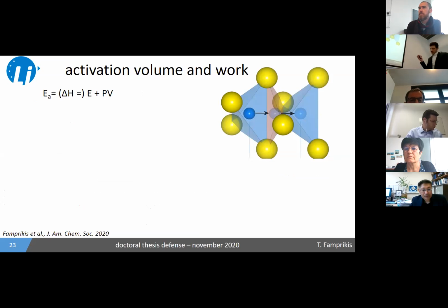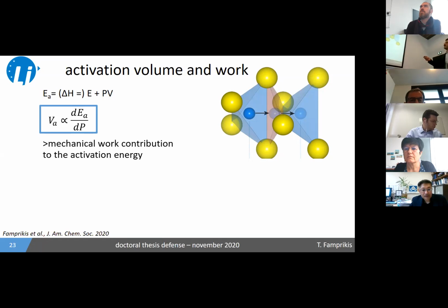remember that what we call an activation energy is more rigorously defined as an activation enthalpy. And as an enthalpy, it has an energy component and a mechanical work component. So the activation volume is nothing else but this volume component here, and it describes basically the mechanical work contribution to the activation energy. As the ion, the blue ion here, tries to go into the very tight bottleneck, there will need to be a local expansion of the lattice to allow for the ion hop. And this local expansion can be understood as the activation volume.